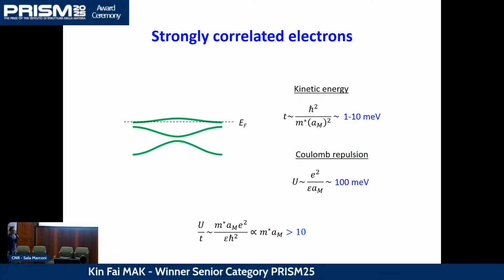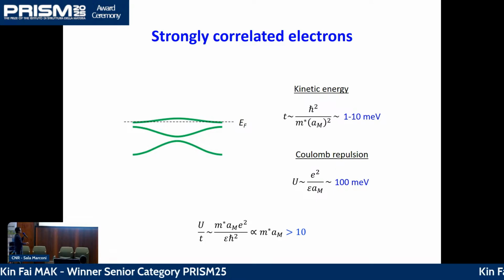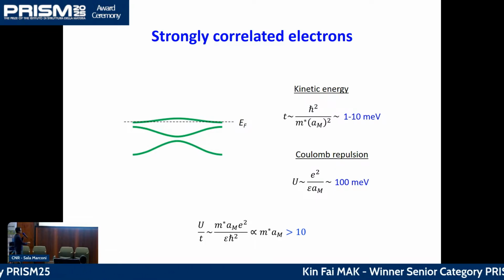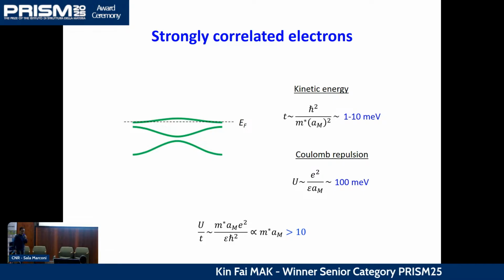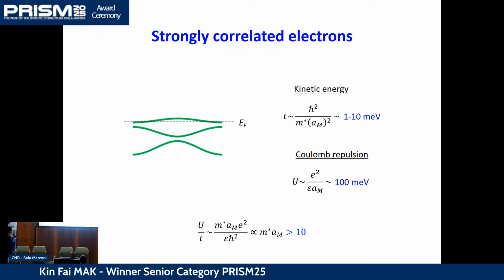One of the bands here is the kinetic energy. The Coulomb repulsion energy, we can take it as the Coulomb form here, and it's proportional to 1 over the moiré period. And typically it is about 100 milli-electron volts. You plug in the numbers.